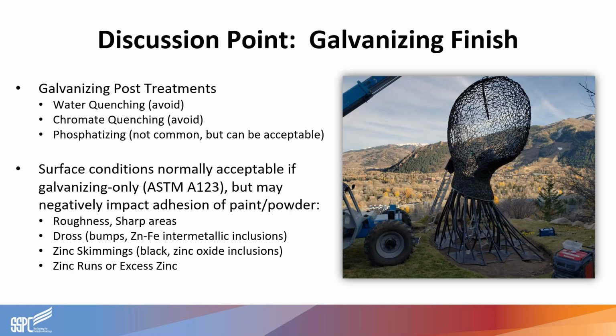So the first discussion point that you're going to want to clarify is the acceptability of any post-treatments that may be performed by the galvanizer. I already briefly touched on this, but the galvanizers apply post-treatments after galvanizing, such as water quenching or chromate quenching, that's going to help them accelerate cooling. There are other methods that can be used to dull surfaces or help prevent wet storage stain, or that white, dusty corrosion products that can tend to form on the surface during storage and transportation.